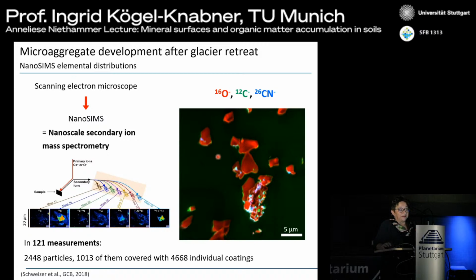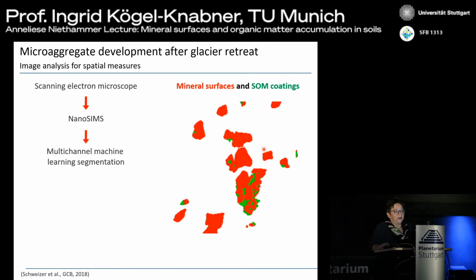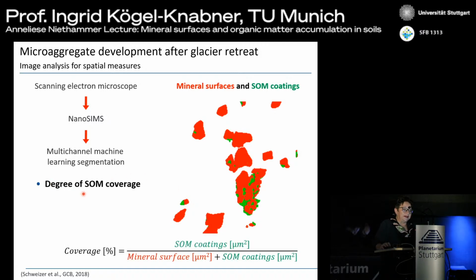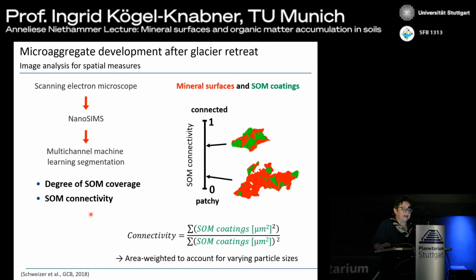And what we did here, we made a lot of these measurements with many parts. So oxygen for the surface, carbon for the organic matter that does not have nitrogen, and CN for the organic matter that also has nitrogen. And we then get a lot of these observations, and first of all, we try to separate the mineral surfaces and the organic matter coatings in our NanoSIMS observations, and we calculate the degree of SOM, soil organic matter, coverage, and also the connectivity of this organic matter. So if they are single spots like here, or if they are strongly connected.